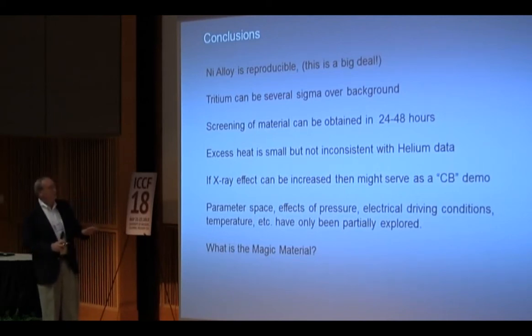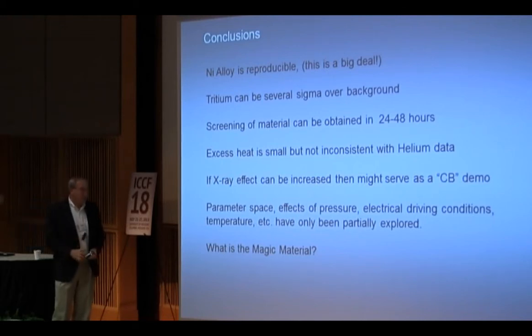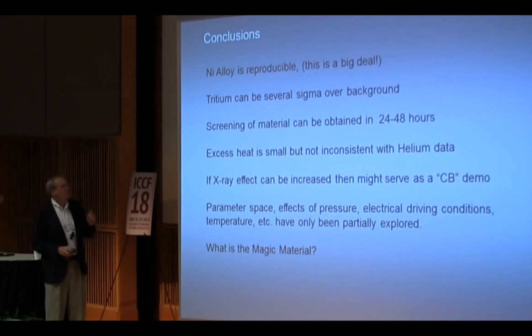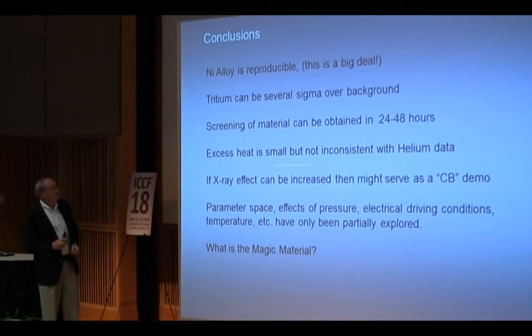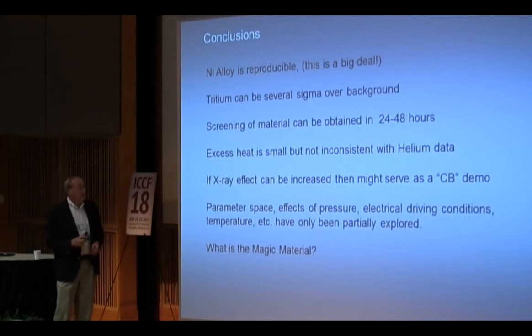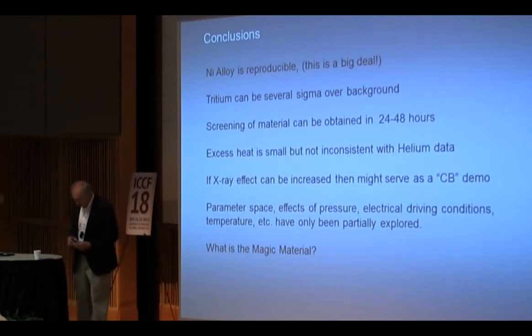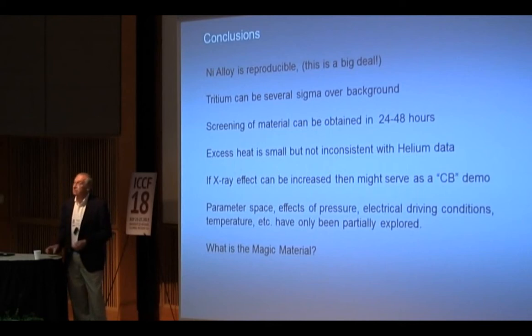But we don't require much material. Your big Milton Roy cell was a huge thing. This requires 150 milligrams of sample. So this excess heat so far is small, but it's not inconsistent with the helium. And if the X-ray effect can be big enough, and we know when to do it, right, 24 hours or less after we turn the cell on, it could serve as a demo. So there's a lot of parameter space here, a lot of materials that have only been partially explored. And what we're doing is we're searching for the magic material. What is it? But palladium and nickel both work. So thank you for your attention.